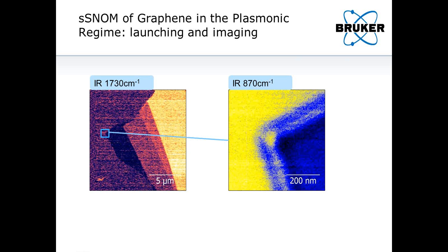So the SNOM on a Bruker AFM is fast without any loss in spatial resolution, as indicated by these images. So as a final result that we obtain on graphene, I would like to remind you of the previous slide that I showed about the point source of a near-field imaging system creating large spatial frequencies.